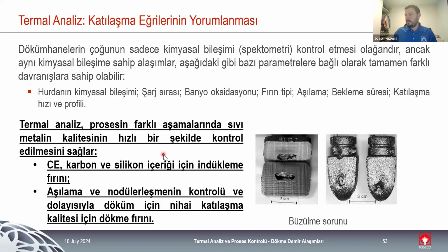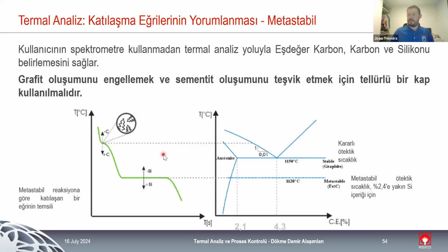And this is just a resume of what we discussed, that we use in the melting furnace the thermal analysis to control the carbon equivalent, carbon and silicon, liquidus temperature to know which point of the phase diagram we are and what type of solidification we have. And after treatment, you use thermal analysis to know the inoculation effect and nodularization effect of the process.